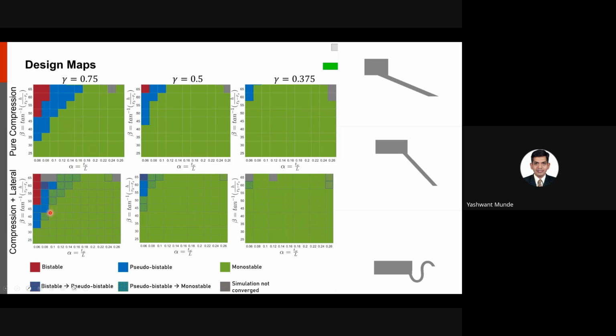And as expected, as we increase the lateral loading, that is eccentricity, that zone reduces, because now the lateral force is pulling the structure back to its original undeformed state quicker. So given your material, you can develop these maps and choose the parameters for your geometry to suit your needs, whether you want a bistable structure, pseudo-bistable, or a completely monostable structure.